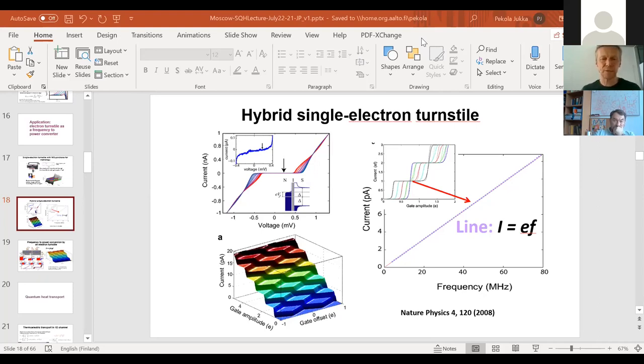Then recently we have used quite a lot of chromium. And with chromium, even with small size, you can reach high resistances. Small size meaning that just with maybe tens of squares in an evaporated film, you can reach kilo ohms, even tens of kilo ohms, and it's quite reproducible. So this is good. And they are relatively linear.